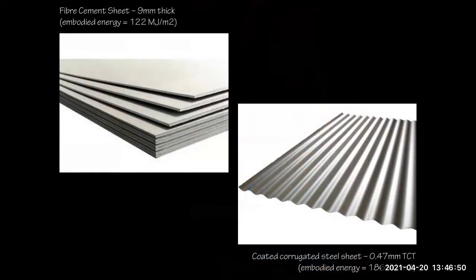But per unit volume, the carbon footprint of steel is staggeringly high compared to all other common building materials, including aluminium. You can see here how 9 millimetre thick fibre cement sheet that normally contains around 40% plantation wood fibre has an embodied energy significantly below that of only 0.5 thick coated steel sheet.